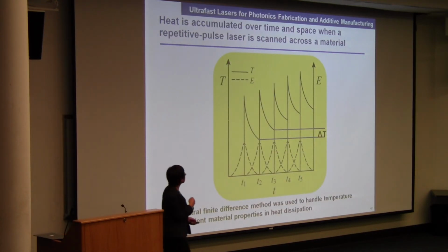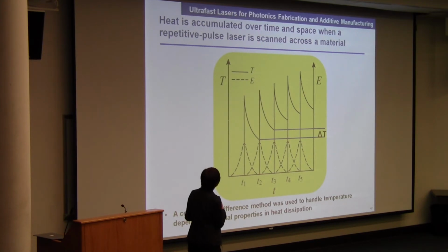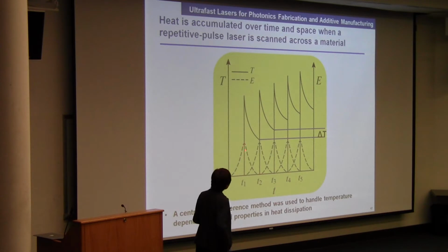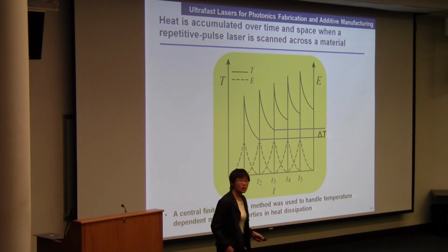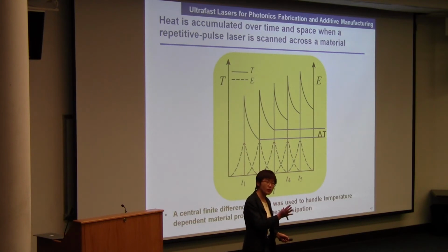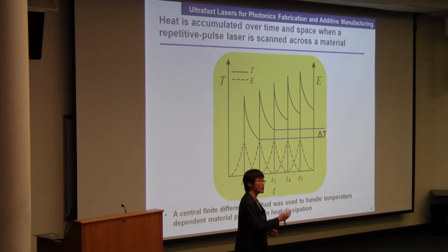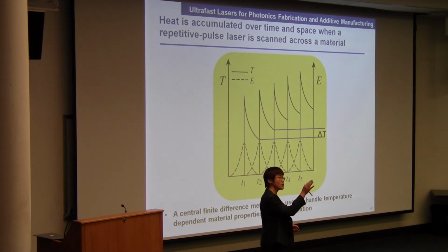When we have multiple pulses, the heat is accumulated over time and space. When a repetitive pulse laser is scanned across the material, you can see that when a pulse deposits on material, the instantaneous temperature rises, and then the heat dissipates. Before it dissipates to the base level, another pulse comes. So there's a repeating process, and there's actually a heat accumulation process. But at the end, you're going to see an equilibrium because the time for the heat to accumulate is equalized with the time it takes for it to dissipate.